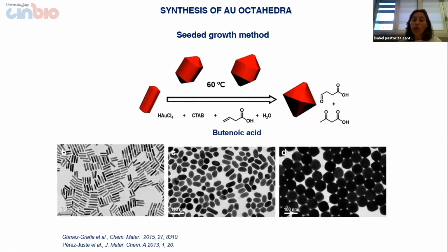First, I will briefly show you the preparation of gold octahedra that will be the nanoparticles chosen to prepare the supercrystals. And we have chosen the gold octahedra because we are able to obtain the nanoparticles uniformly, and also because they present sharp edges and tips, and this is nice to produce hot spots. So the preparation is a seeded growth method where we start with gold nanorods. Using butenoic acid, we reduce a gold precursor selectively on the nanoparticle surface in order to obtain the octahedra.